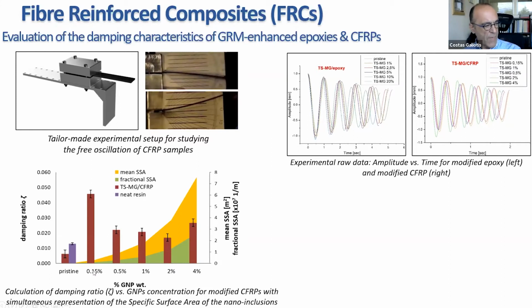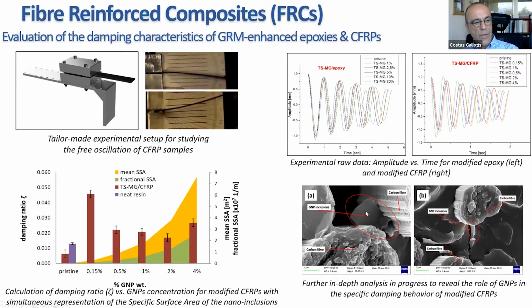You add 0.15% of graphene and it shoots up quite considerably. Then it starts falling down again. And the yellow and the green curves are the interface areas. So the interface area where you have a high interface area which enhances the damping is still small at 0.15%. When you keep on increasing, it doesn't necessarily give a linear increase in the damping, the zeta parameter, the damping characteristics. Again, the reason for that is when you have highly dispersed graphene or graphene attached to the carbon fiber surface, all these structures will be highly dispersed, or the friction of graphene with the carbon fiber itself, all these are helping to increase the damping of the structure. But if you go to very high percentages, then you will see you lose this.